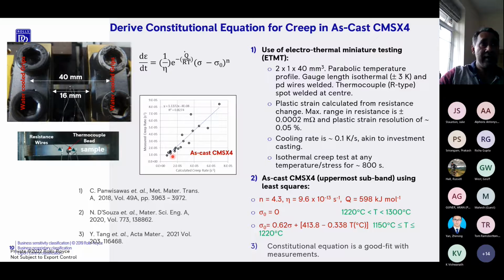Well, the fit's not too bad. You can clearly see that there's a reasonably good fit between the experimentally measured creep data and the constitutive equation that we have derived based on least squares. So one of the principal applications that we've used miniature testing for is in the development of a constitutive equation for creep. And this is an equation that the process modeling people within Rolls-Royce can use to model the evolution of plastic strain and stress in the prediction of recrystallization.